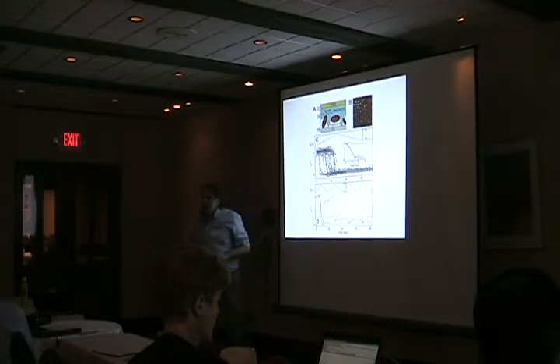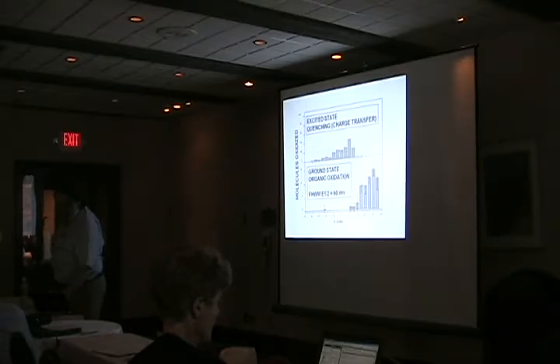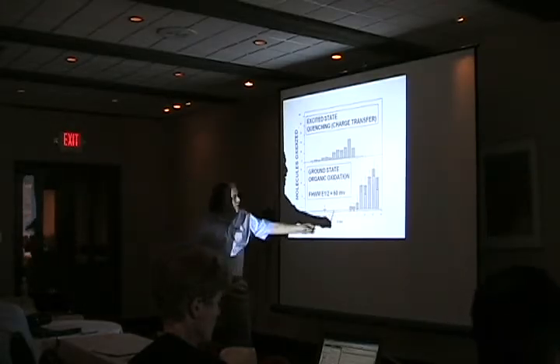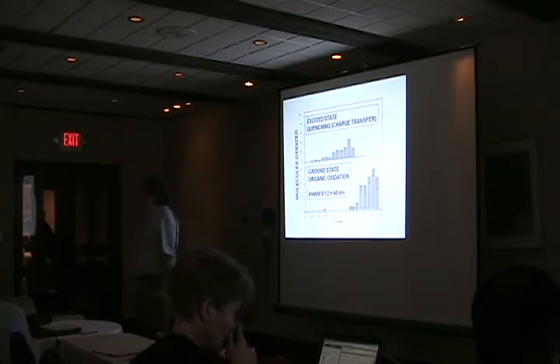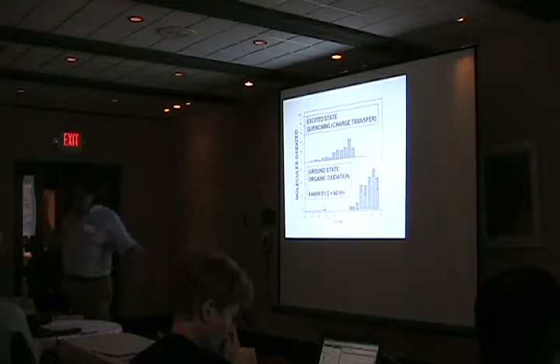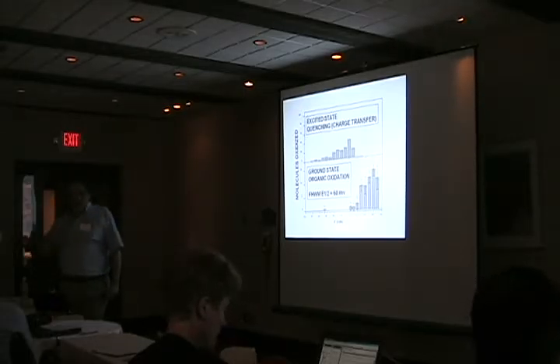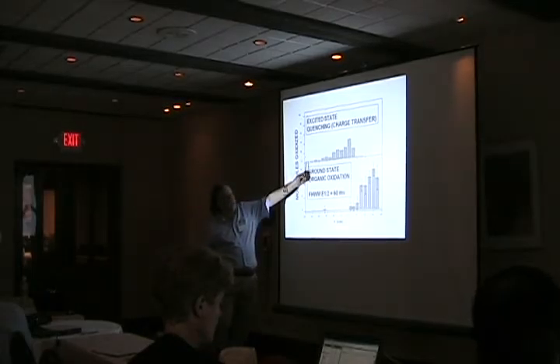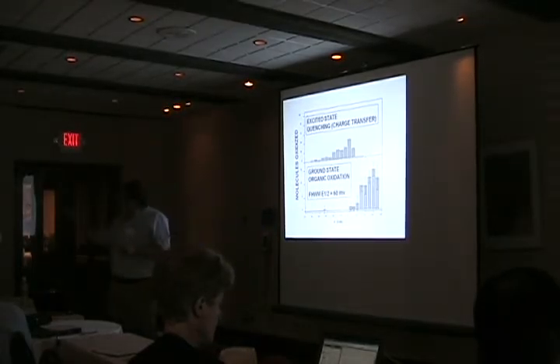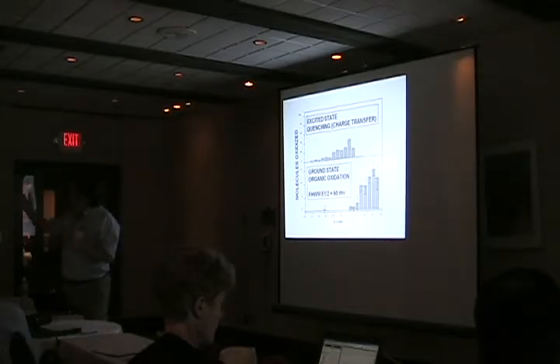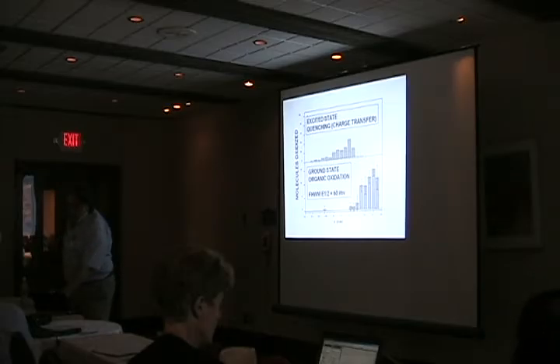So these are oxidation reduction curves in the device where there is an electrolyte, and using electrochemistry we determine the quasi-Fermi potential very precisely, and we were able to not only measure the onset for oxidation in the ground state and measure E0 or E1/2, depending on what your HOMO energy, the beginning of the HOMO distribution, but we were also able to do it for the excited state, the one that's produced by a photon, and it's stuck on an electrode, and that's what John's going to talk about in his poster, because the molecule's stuck on an electrode and you can shine light on it. You can then very precisely investigate the electron transfer with the electrode.